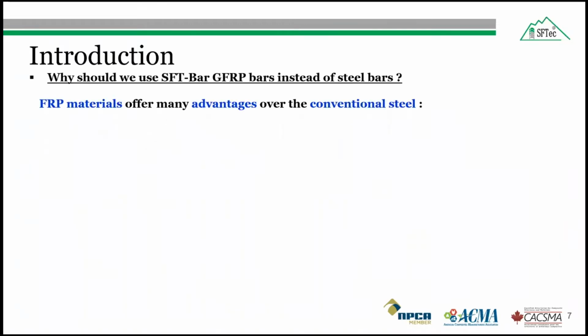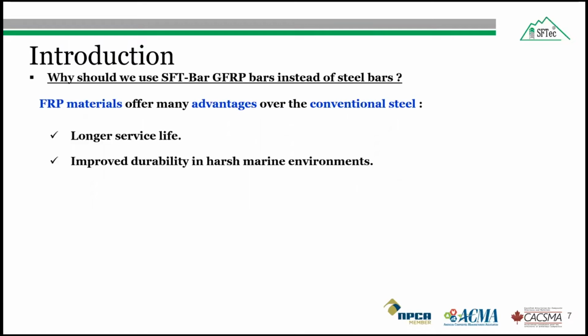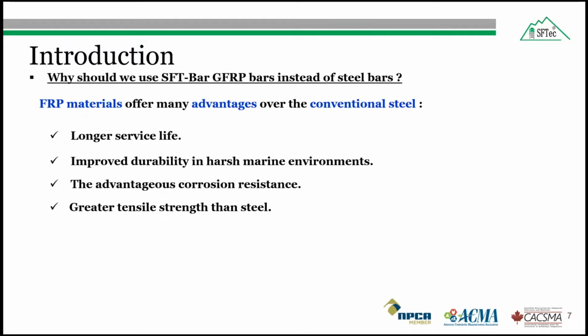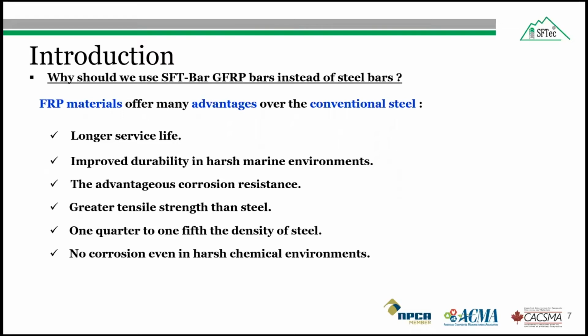Some of the advantages of SFTec glass fiber reinforced polymer bar over conventional steel bars are: it has a longer service life because of its corrosion resistance, therefore improved durability in harsh environments such as construction near coastal areas and North American cold climate. FRP bars have better resistance against corrosion compared to steel bar. As I said earlier, the tensile strength of FRP bar is 2 to 3 times more than that of the steel bar. FRP bars are lighter due to low density compared to steel bar, and due to corrosion resistance, they are good for harsh chemical environments as well.